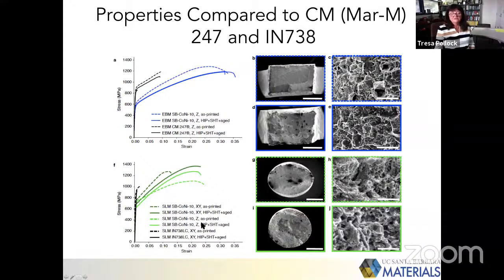And again, as I said earlier, the SLM process has a lower preheat, and so finer structure and greater tendency for cracking. So here the nickel alloy is 738. You can see that in printed or solution heat treated and aged forms, we have very, very limited ductility. But the cobalt nickel alloy then again has fairly high strength and good ductility.